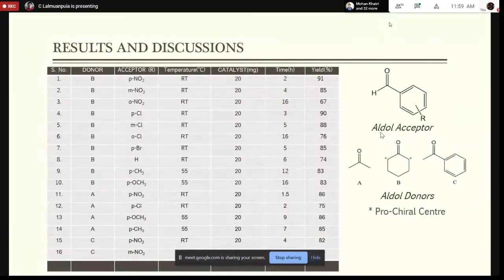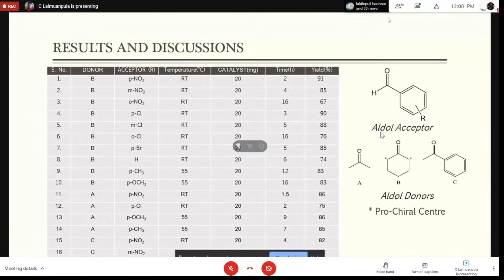And here is a table showing the observation data of the reaction. The catalyst loading is fixed to 20 milligrams. The reaction time shows that electron withdrawing groups in the aldol acceptor increase the electrophilicity of the aldehyde group and ultimately the reactivity as well. However, an electron withdrawing nitro group in the ortho position takes a very long time to complete. This may be due to intramolecular hydrogen bonding between the aldehyde functionality and the adjacent nitro group. In case of substituents with electron donating groups, the electrophilicity decreases and thereby the reactivity. Hence, an elevated temperature of 55 degrees Celsius is required to carry out the reaction.